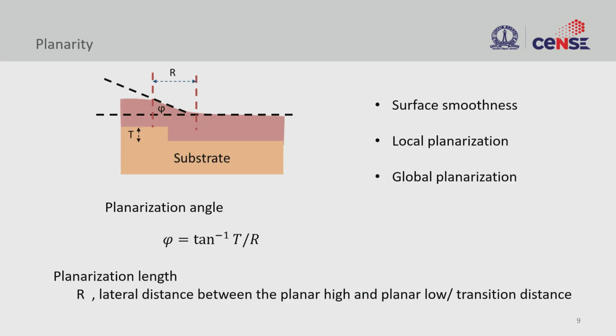And this is how we characterize the planarity, right. So planarity is nothing but what is the angle between the global flatness or the local flatness that you have, and this strongly depends on the topography that you start with and the material that you have, and also the flatness that you are looking for, okay. So based on this, you could characterize the flatness, which is nothing but the topography over the length scale, right. So how far are these two flat surfaces with respect to the topography that you have.